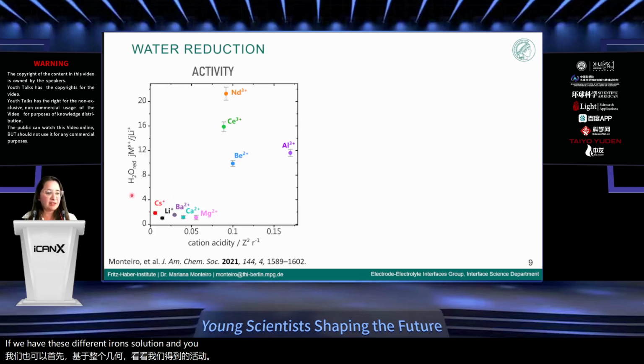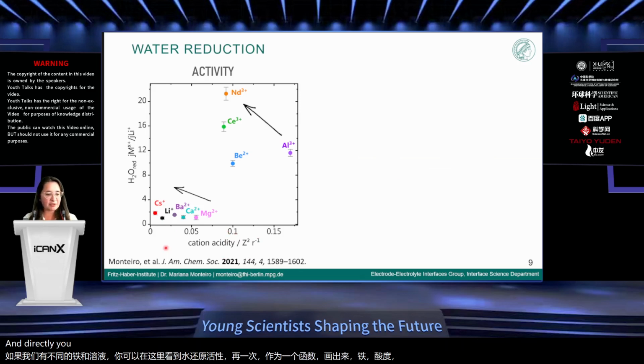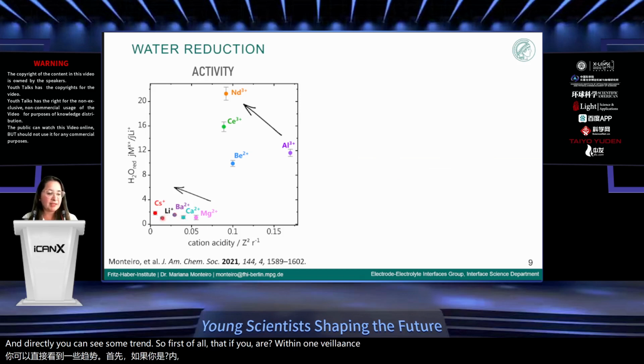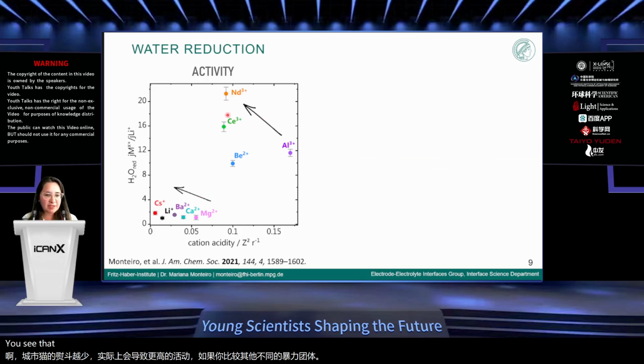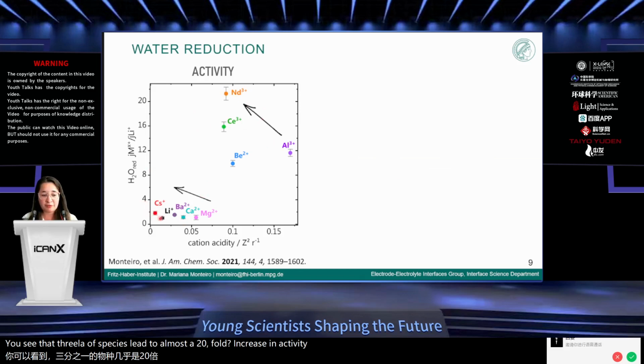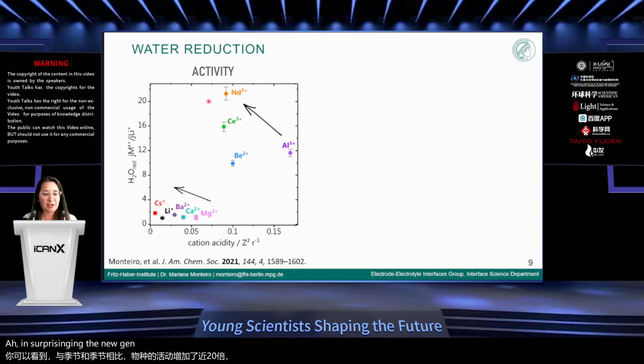And you'll see here the water reduction activity, again plotted as a function of cation acidity. And directly you can see some trends. First of all, if you are within one valence group, the less acidic cations actually lead to higher activity. And if you compare the different valent groups, you see that 3+ species lead to almost a 20-fold increase in activity compared, for example, to cesium and lithium. And surprisingly, neodymium is actually one of the best performing ions.